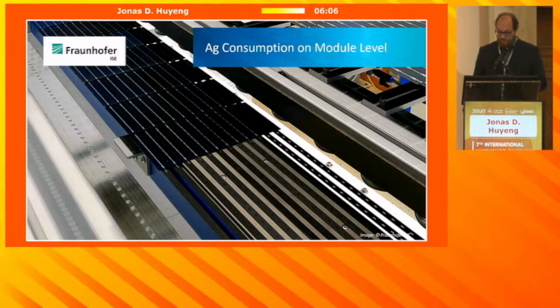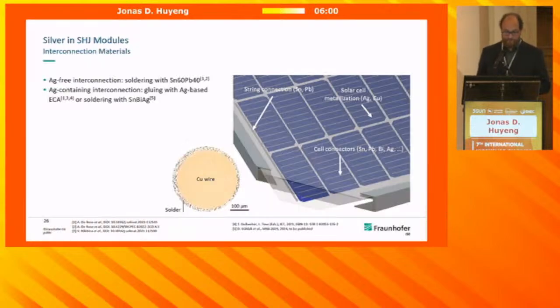So let me take 1-2 minutes to think about the module level and the silver consumption that we have on module level. Basically, there's different parts where silver can be consumed. Of course, there's the string interconnection, the cell interconnection, and typically you would want to do the string interconnection with a silver-free interconnection because it's not that important. But if you're having another solder here, then of course this can also contain silver. And then if you're going for ECA, of course the conductive particles are silver. We are leaving this out for another day of discussion. Here we want to focus on the low temperature soldering with